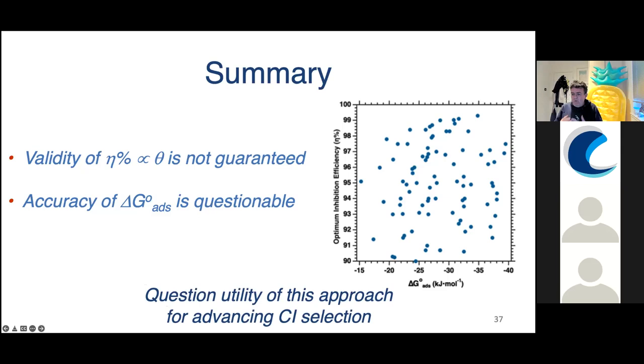What we're thinking we would see is some correlation between the inhibition efficiency and delta G. But you can see here, it's simply a scatter plot. So how can you expect to use these values of delta G, even if they have some value at all, of picking out a good corrosion inhibitor? Because there doesn't seem to be any way of doing it from this work. So I think this is a rabbit hole that we should avoid going forward, because I think there's not so much use in it.